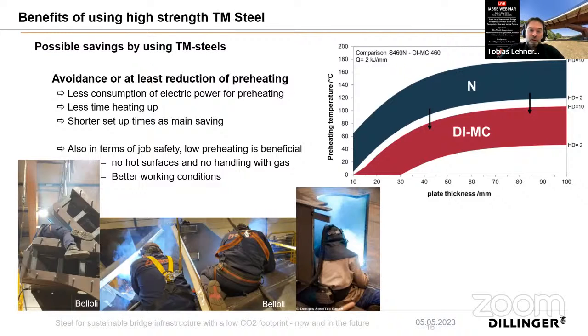They can be welded without, or at least with a significant reduction of, preheating. And this is again, of course, energy which can be saved, and that means also CO2 emissions. Besides that, it's also very important for job safety, because you do not need to preheat. And if you have a look at the pictures shown here, you can imagine that preheating the structures and welding then is quite hard work. So if you can avoid the preheating, it also is very good for job safety.